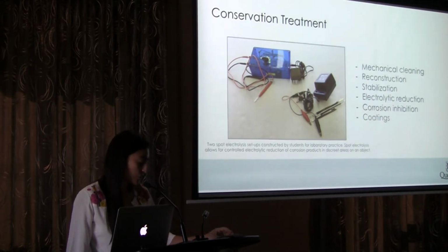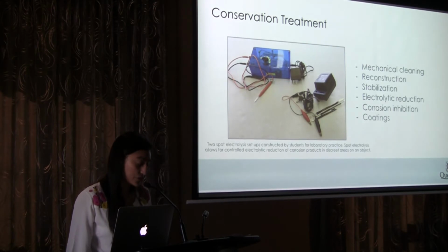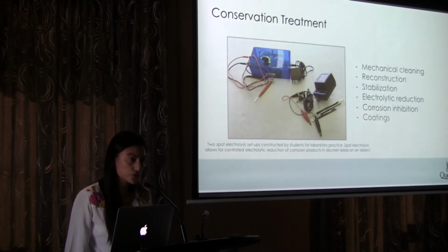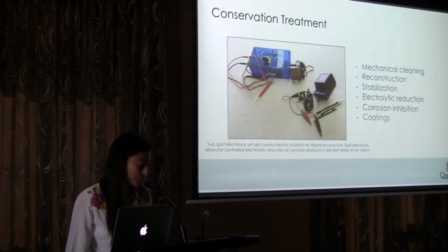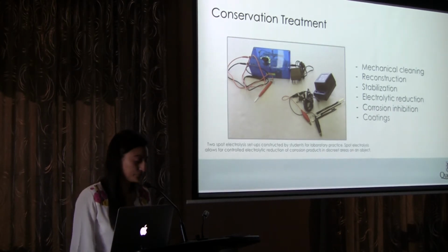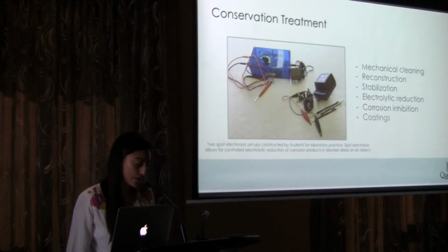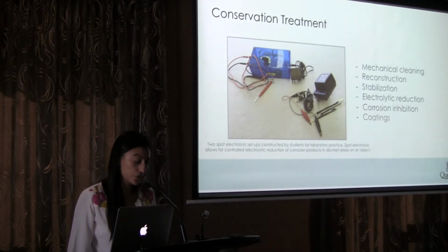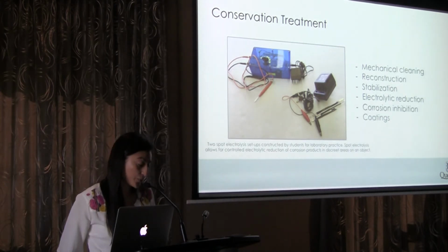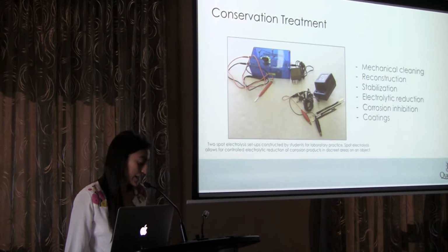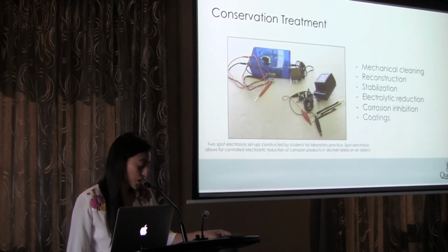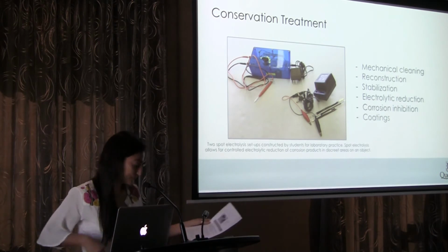Corrosion inhibition is also a metal conservation technique. After we have clarified the surface of the corroded metal, we want to reduce the risk of future corrosion outbreaks. We do this by artificially creating a passive layer of corrosion on the object, a layer that is both unintrusive and stable, meaning that it does not attack further the metal core of an object. We have applied tannic acid to wrought iron objects and benzotriazole, or BTA, to copper and copper alloy objects as corrosion inhibitors. We also apply coatings to Herstmonceux objects because they will be used for study purposes.